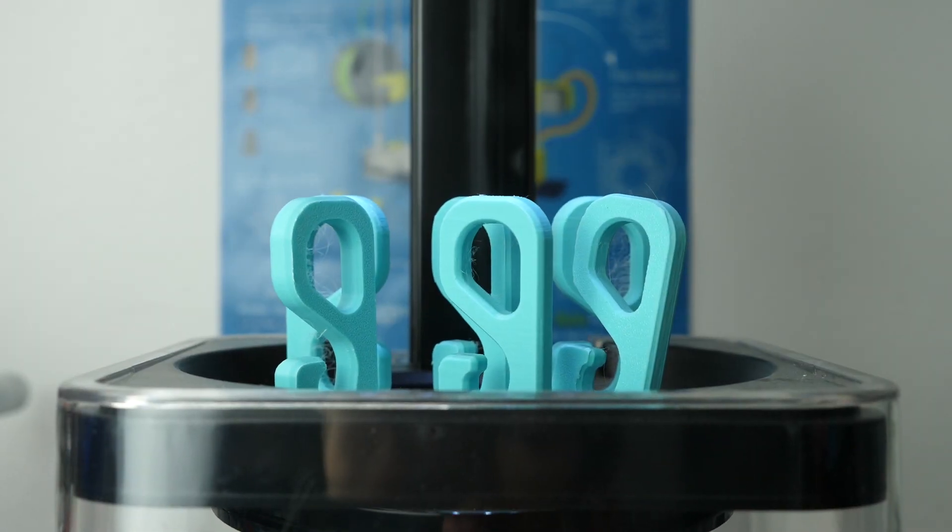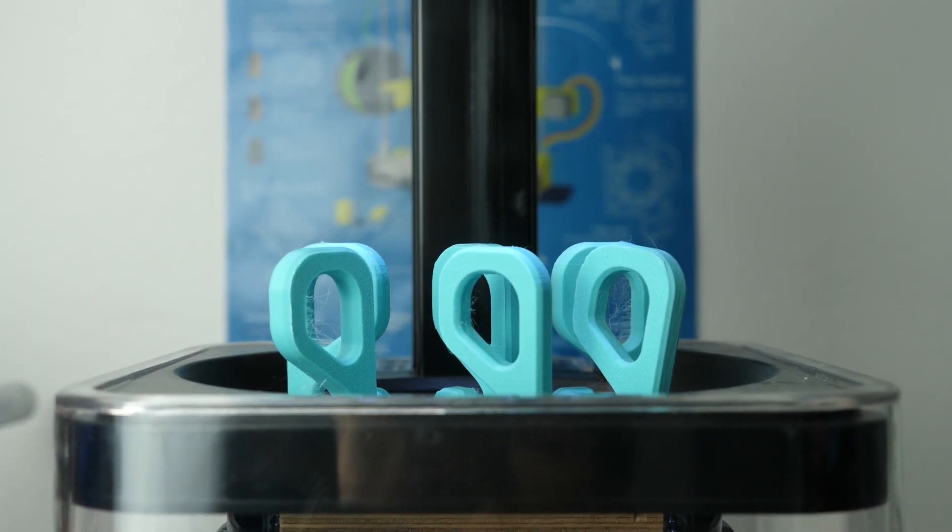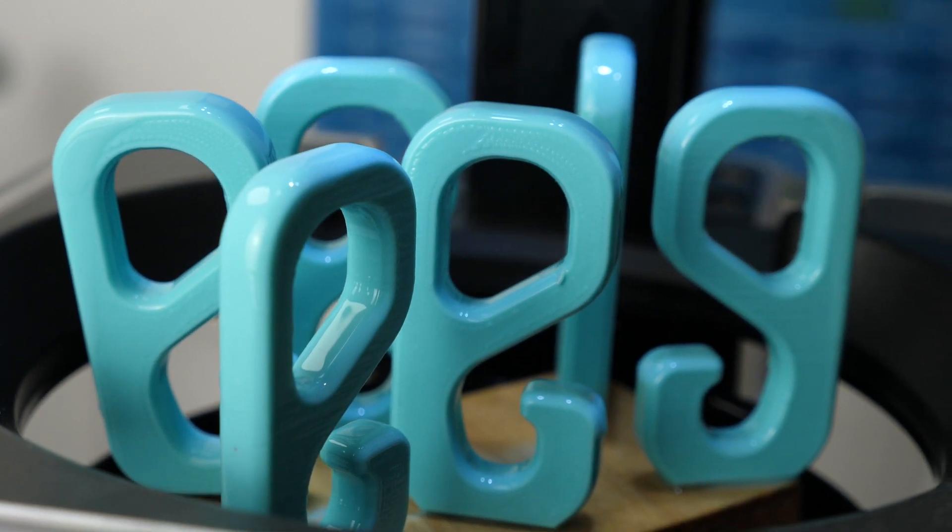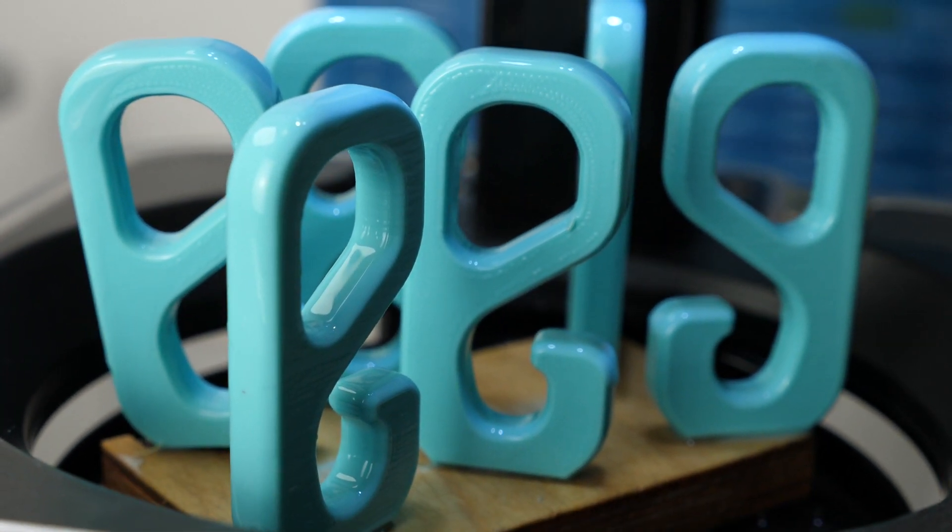The polysmooth parts were treated for 40 minutes in the polisher using 99% isopropyl alcohol. These looked very nice and shiny, still keeping a bit of details because I didn't over smooth them.